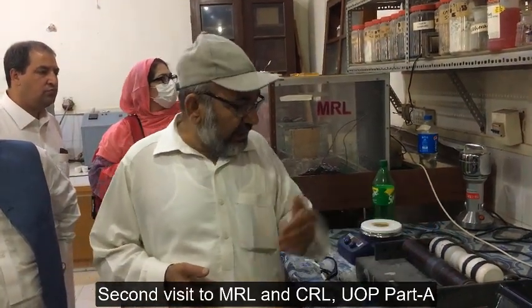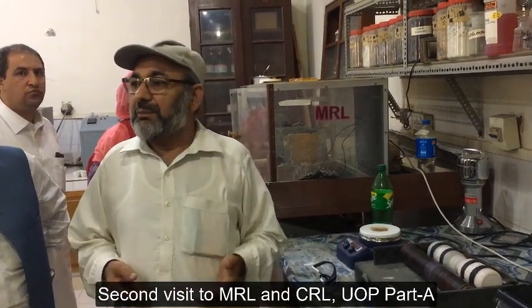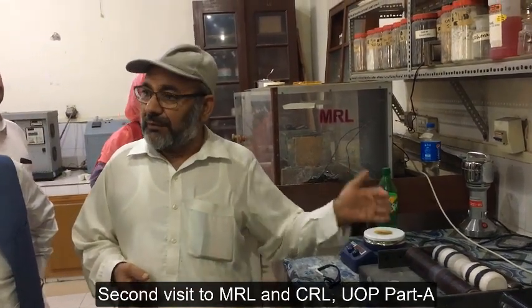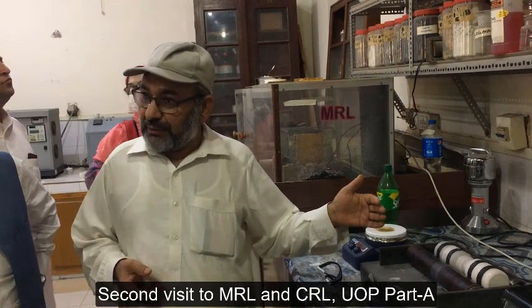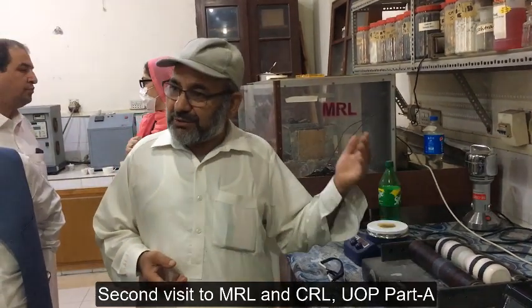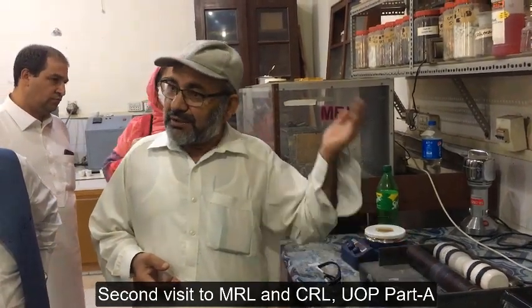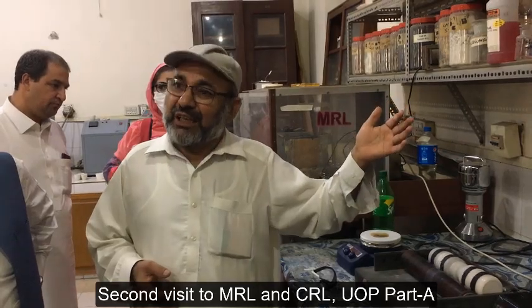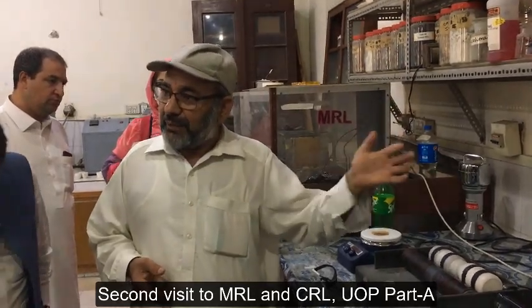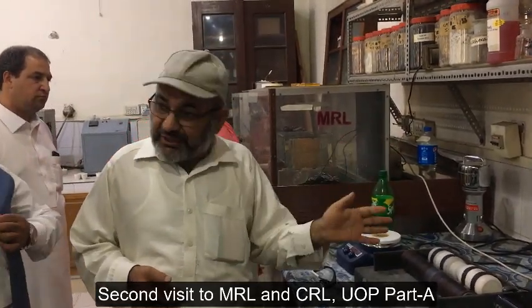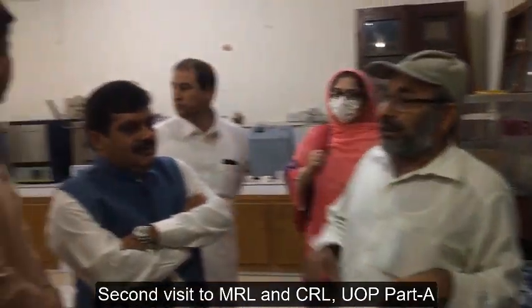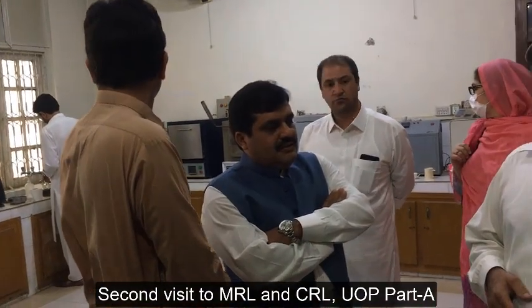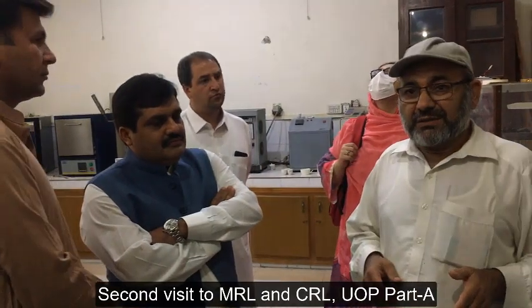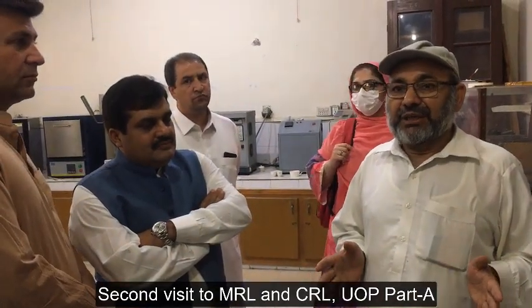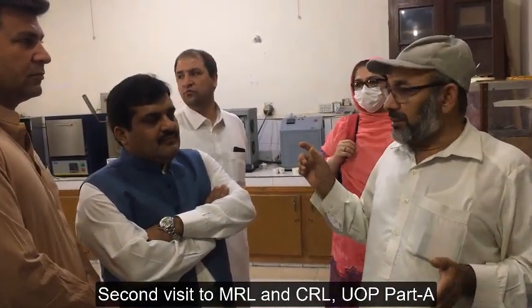And we place it here, and depending on the required particle size of the final powder, right? We keep it here for 2 hours, 20 hours, 10 hours. People keep it for many days if they need the final particle size. When we get that, then we take it to the drying oven and remove the balls, the grinding media, and they are dried overnight.